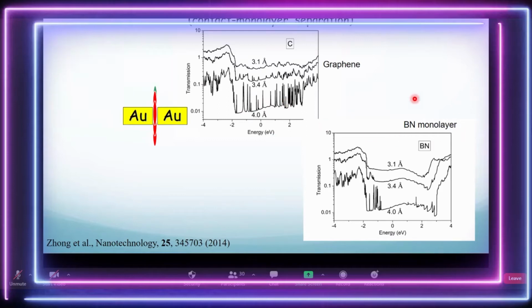If you look at the boron nitride, remember boron nitride is semiconducting, it has a gap. And like we found earlier, when the contact to boron nitride distance is small, we still have the finite density of states and transmission function. But as you increase the distance, it goes down, and at the weaker bonding case, you can see it mimics the semiconducting behavior. So this again is a computer experiment, which shows you that even at the monolayer level, the interface dominates, and if you weaken the interface effect, then the material's intrinsic property is reflected in the IV curve.